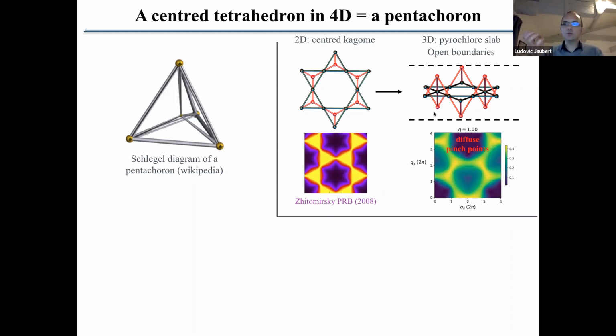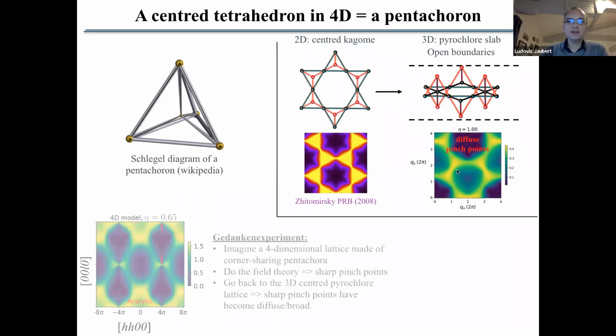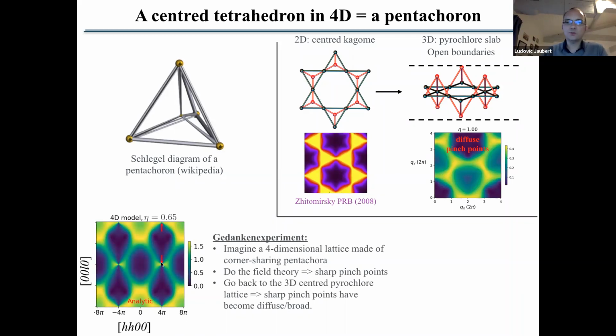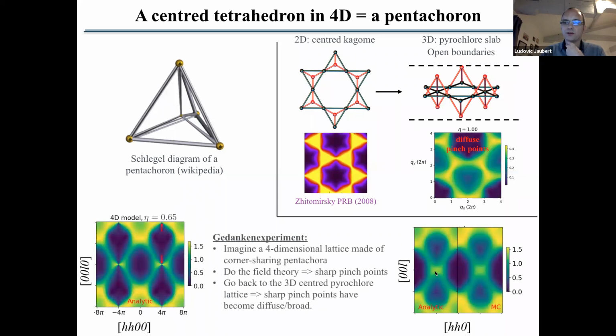So this divergence-free condition I was talking about is not constrained within the 2D plane or the 3D slab. It can exit the system through this extra dimension. This exiting of the magnetization flux creates diffuse pinch points, because these pinch points really come from the zero divergence condition locally. Because you lose that, you get diffuse pinch points. In our centered pyrochlore lattice, which corresponds to a slab of this 4D one, you get only diffuse pinch points, with a good comparison between analytics and Monte Carlo simulations.